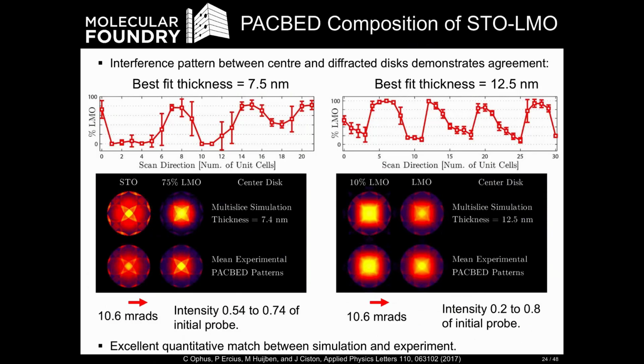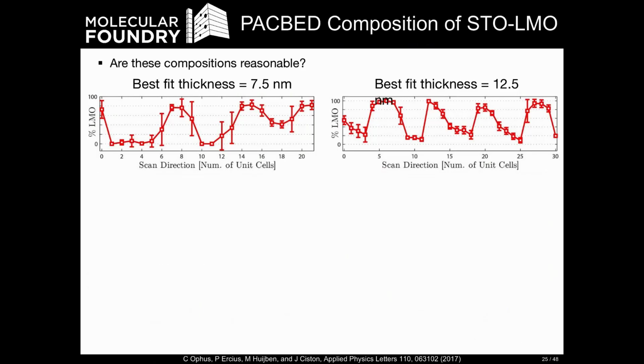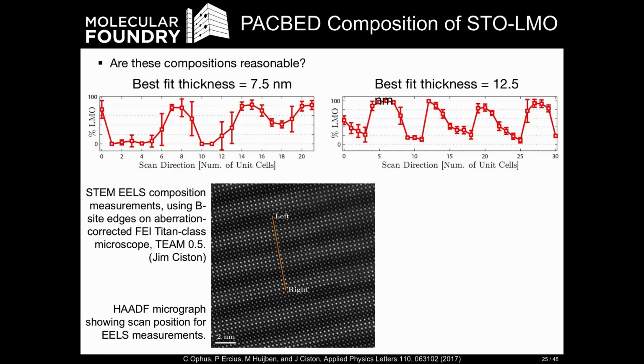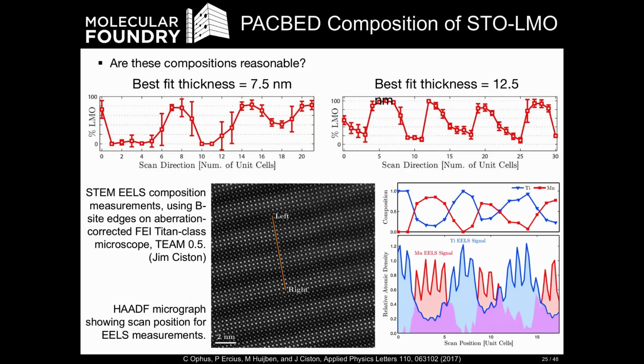And if we want to double check these results, we could compare them to a traditional EELS measurement, in this case using the B-site edges on our aberration-corrected microscope. If we plot that composition, we see it alternates between about 0% LMO and about 80% LMO. So it's in very good agreement with our PACBED measured compositions. Okay, so that's the very simplest 4D-STEM experiment. You compute a library of diffracted patterns and you compare them directly to your experiment.